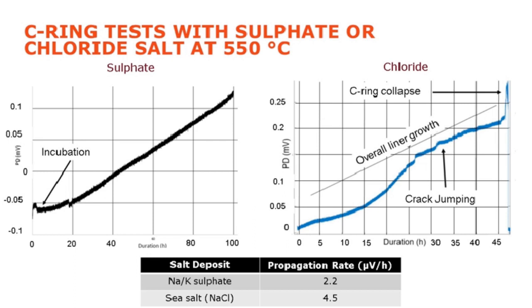So we can see that the rate at which potential drop is increasing is twice as high for sea salts, so that chloride-based salt, at these temperatures on these alloys. So it's highlighting the significance of what the deposit is actually made of, or what the composition of the deposit is, for this mechanism.